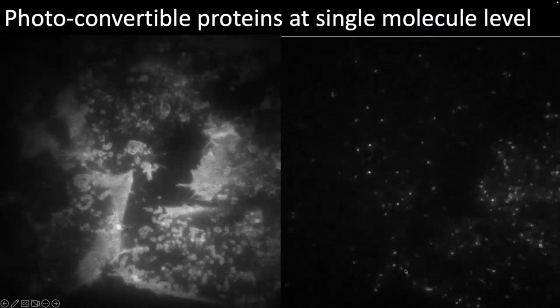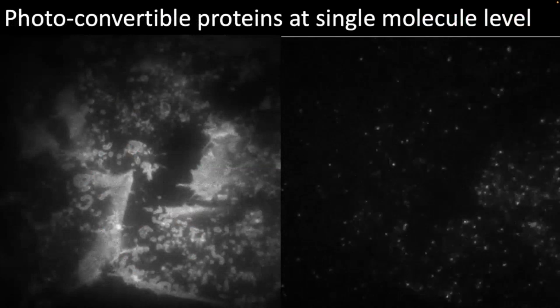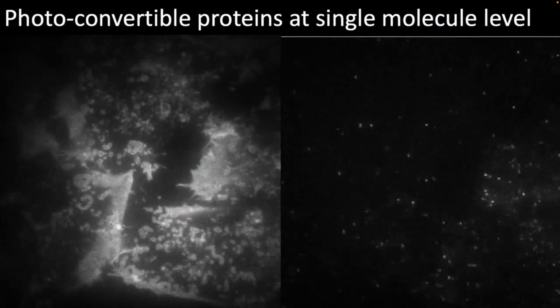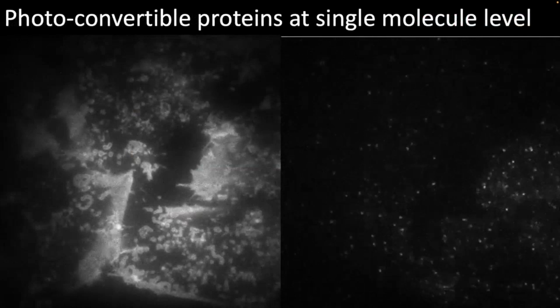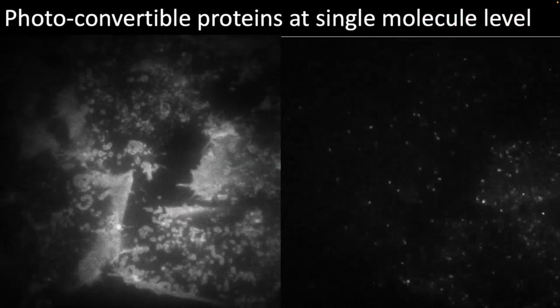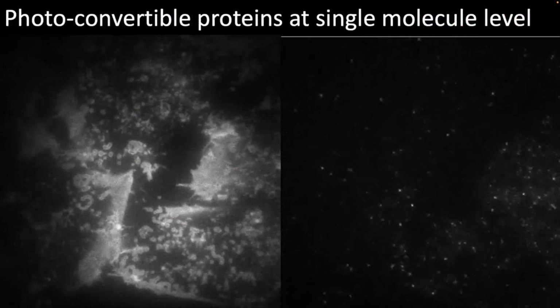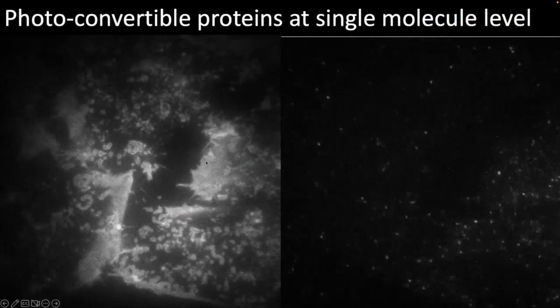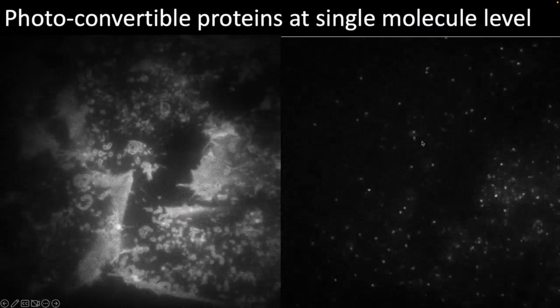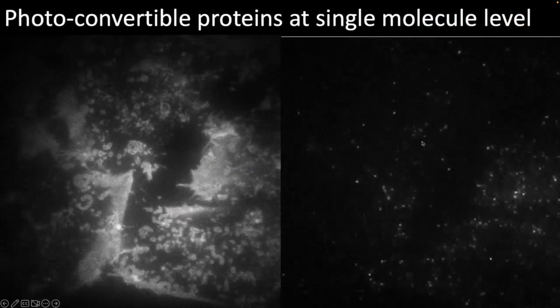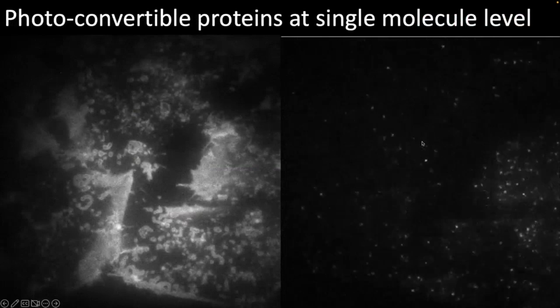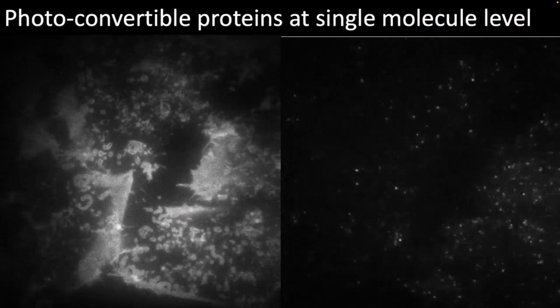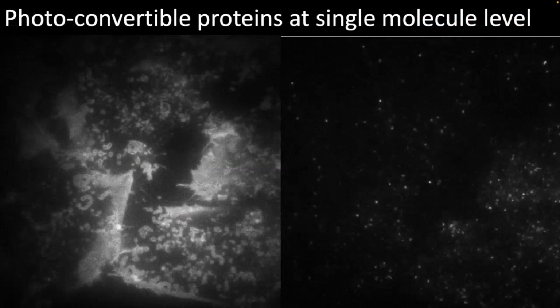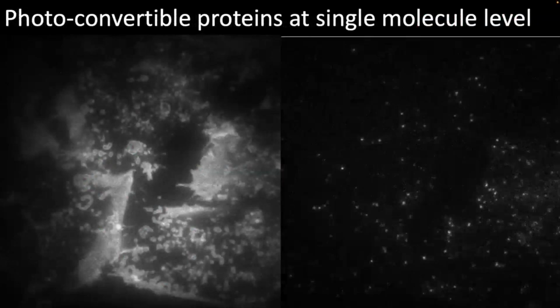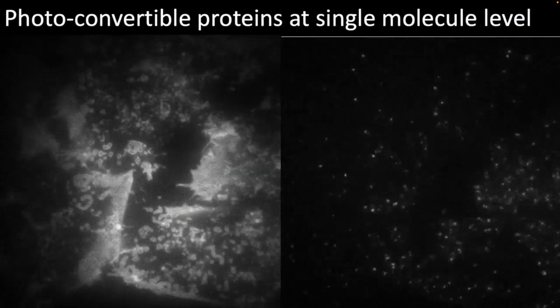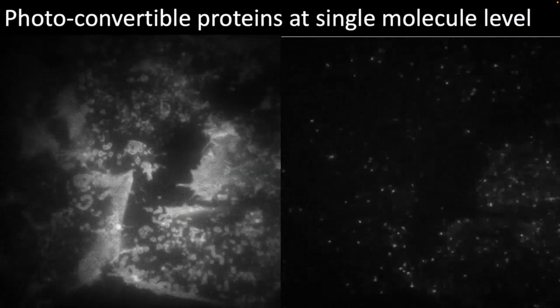And then if you just acquire a data set, you see this kind of blinking. So what happens is that in every frame, there is this continuous, very weak illumination with ultraviolet. And in every frame, there is a different subset of molecules that are converted from the green to the red. They are converted, and then they are imaged with 560 nanometers excitation, and then they bleach, or they go to a dark state on the red. So you see them for a few milliseconds, and then they are off again. So you have this on and off behavior, and every time you are activating different molecules.